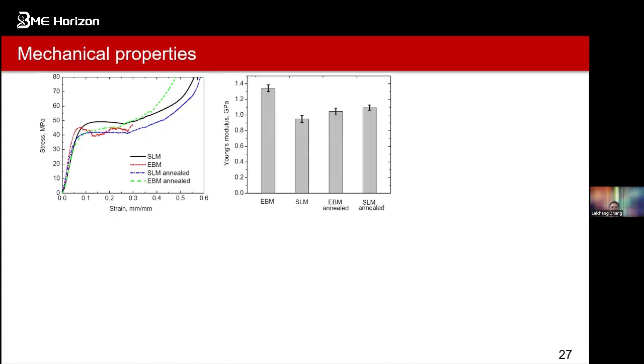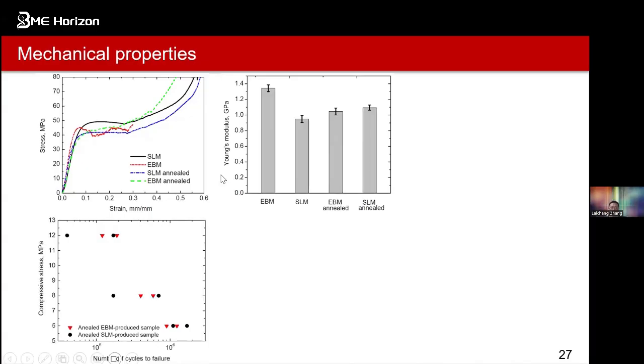But also we can see the Young's modulus, compared with the homogenized beta, is almost similar or comparable. But the interesting part is the fatigue. The fatigue strength of the EBM and SLM beta titanium is of course sensitive to the stress amplitude. At the lower stress levels, for example at 6 megapascals, you can see this one is roughly equal. The fatigue behavior of the mesh is mainly determined by the cyclic region and the surface properties of the struts, resulting in similar properties for both manufacturing processes.